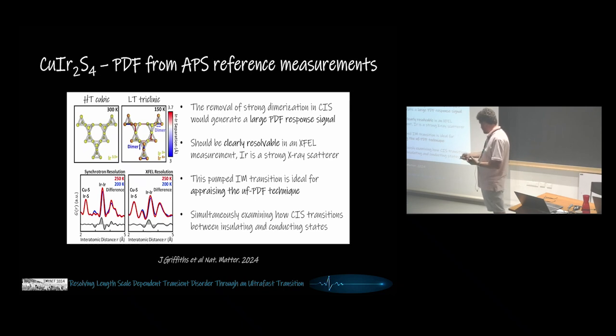So you see here a comparison of the PDF profile above and below the temperature-driven phase transition, and you see clearly that there is a dimer peak. Now, this is a very high real space resolution measurement in that we actually had access to 30 inverse angstroms Q. Now that we have that data, we can degrade it to the expected Q range of the LCLS measurement that we are just about to do, and see if we can still see this temperature-driven phase transition, and the answer is yes.